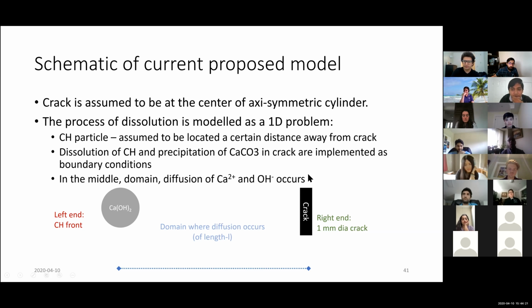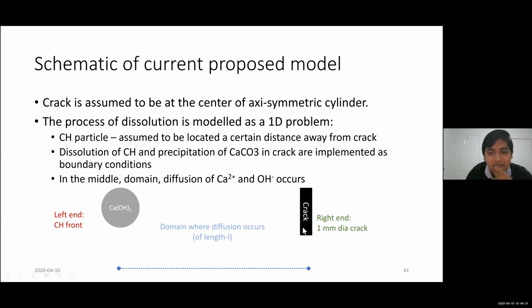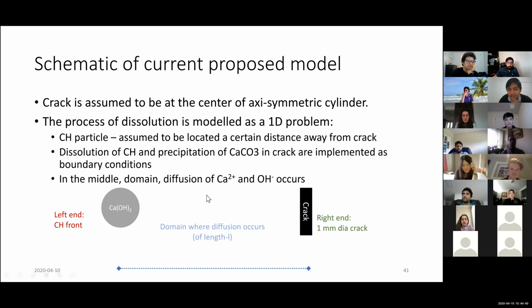So I assume that there are carbonate ions inside the crack, since it's there in the water as a curing mechanism that I have used in my experiments. So if sodium carbonate is present here, then what has to happen to fill the crack is calcium has to dissolve here, and then it has to travel this length in concrete and reach the crack.